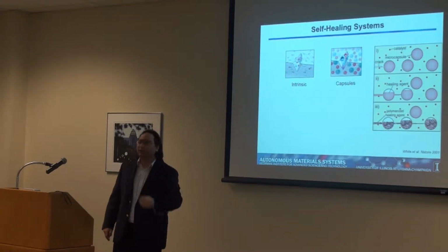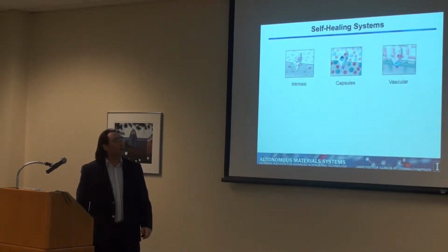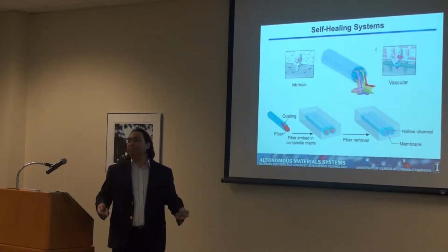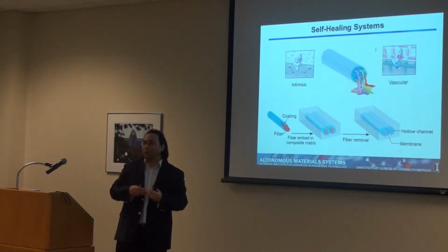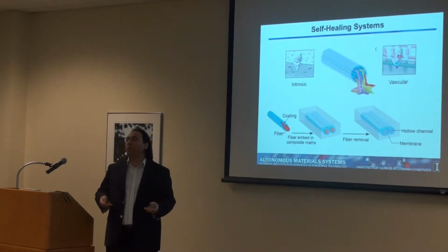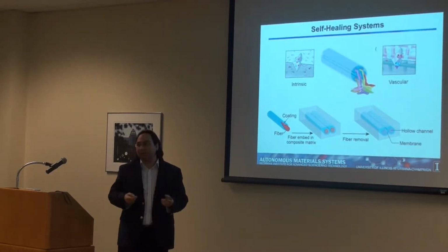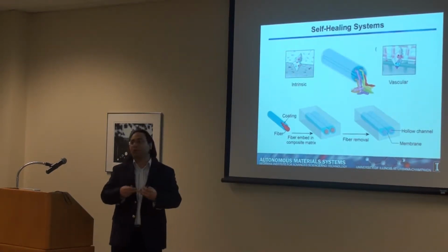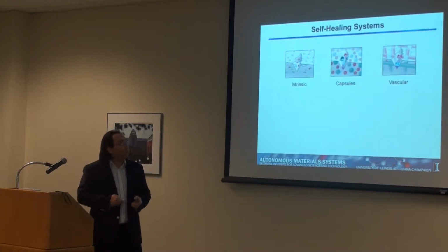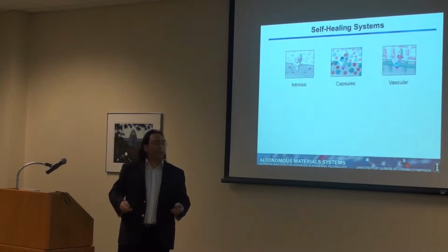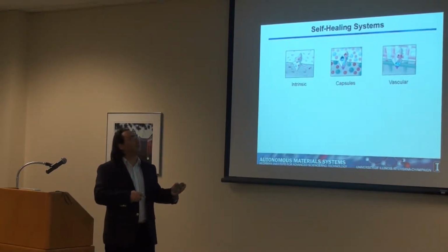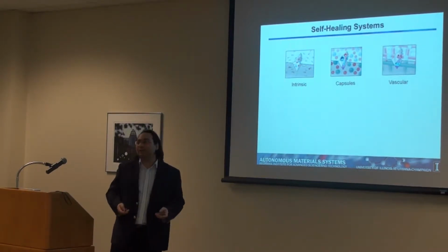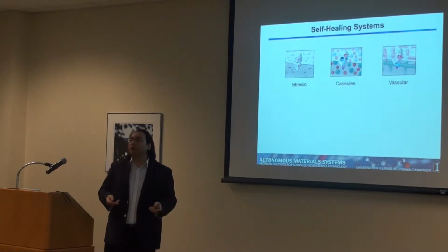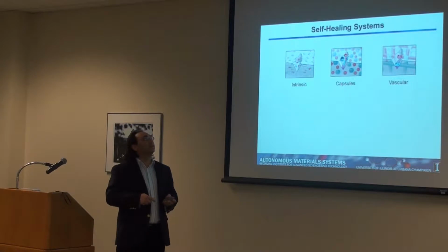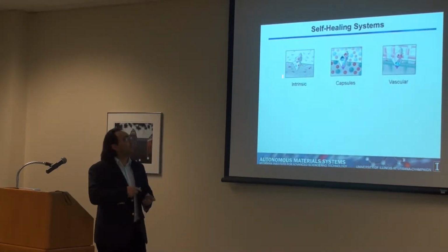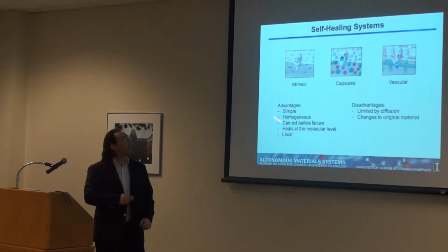And this is a very interesting system. It's already even being commercialized. Recently, we've been working on vascular systems. So we basically make materials that have hollow channels in them, and again we can pass, for example, a healing system, a monomer, through these channels, and when you have a crack, it opens up these channels. The liquid can come into the crack, fill the crack up, polymerize, and close the crack. Now, these three different systems are being developed in our group, and there isn't a best one, right? They have different applications. This obviously is a very complicated system, and you can use it, for example, for airplane ships or hulls, or something that is very complicated, and the damage gap that it can heal is much larger than this system, which has its own properties, and this is the one I've been working on.